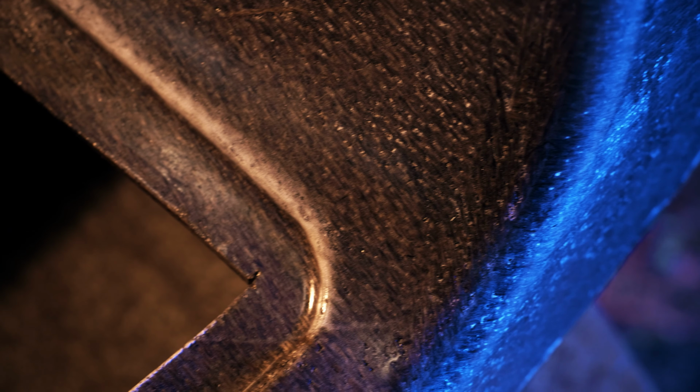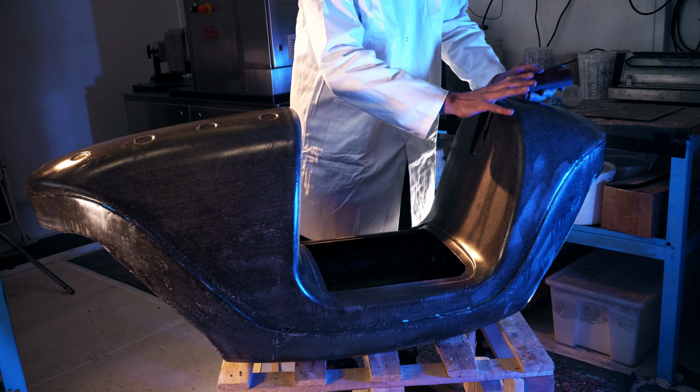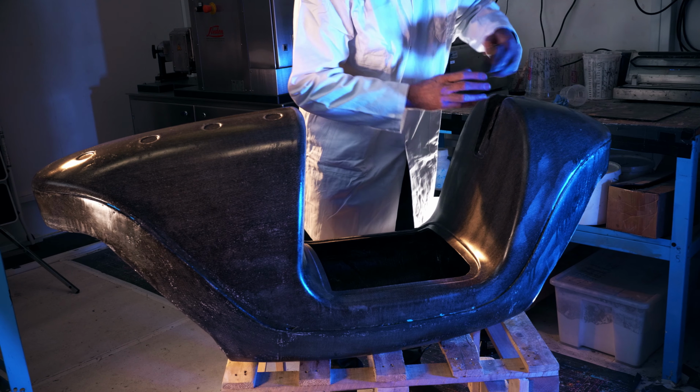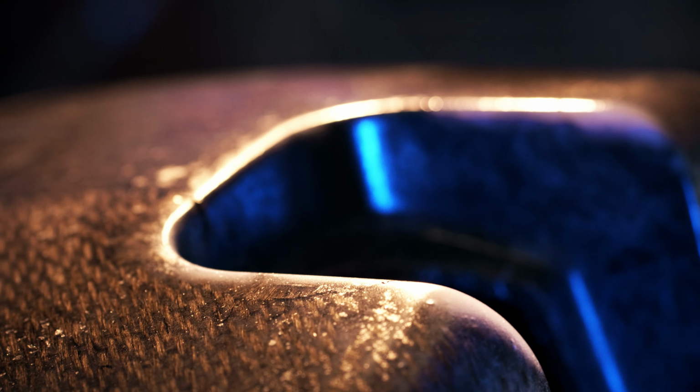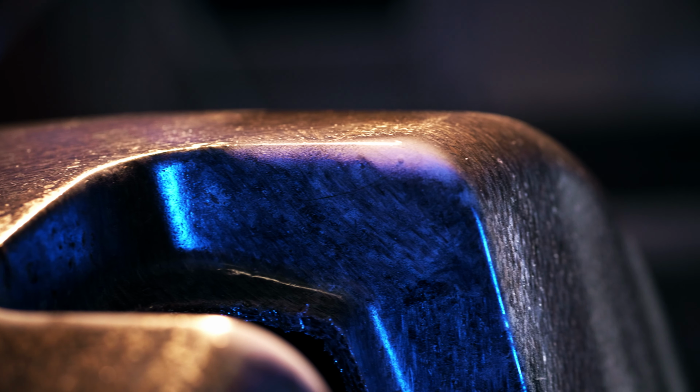The scooter is a perfect case for testing and demonstrating use of high-end biocomposites in mobility applications. In the SSUCHY project, the monocoque was redesigned and optimized to increase the bio-based content from 30 to 65%, save mass by approximately 55% and decrease the expected labor time to 50%. The optimized design was implemented in a prototype as a proof of principle made of woven hemp fabric and cork.